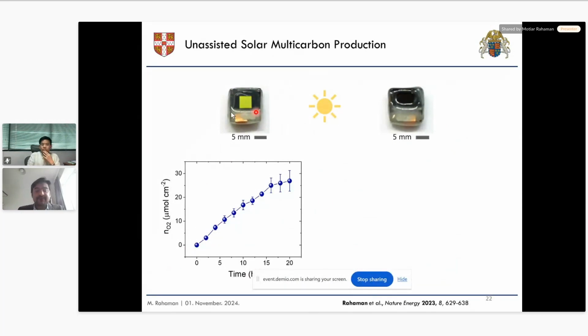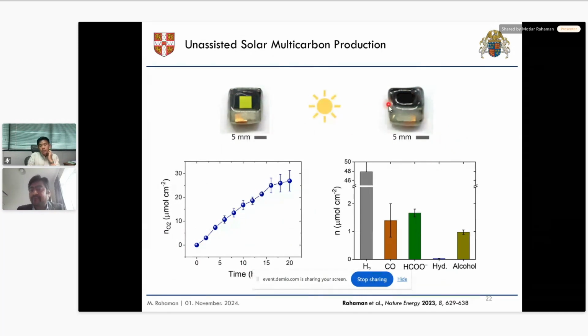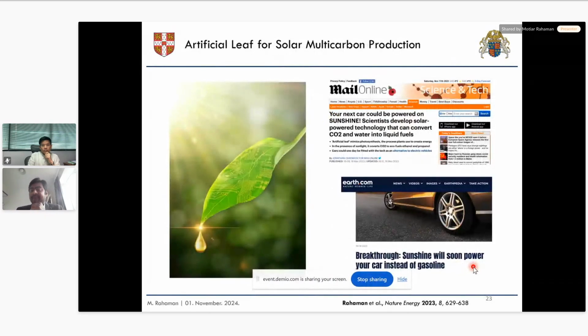With time, from the photoanode we get gradual oxygen evolution, and from the photocathode, along with other products, we get multi-carbon alcohols. The multi-carbon alcohols are C2 and C3 together in an almost 1:1 ratio, that is ethanol and n-propanol. And this is the very first standalone artificial leaf device that can convert carbon dioxide into multi-carbon alcohols, even C2 and C3, ethanol and n-propanol, using sunlight as the energy source without requiring any other external energy.